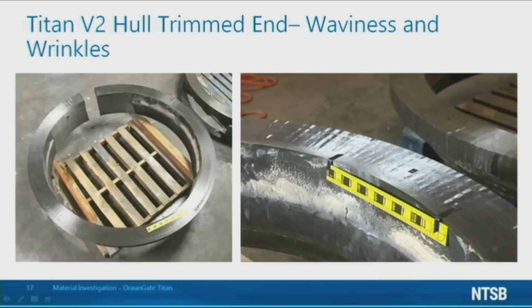The image on the left is an overview image of one of the trimmed ends. The image on the right shows a portion of the through thickness face under oblique lighting. The oblique lighting reflects off of the composite plies based on their orientation. The periodic light-dark reflections are an indication of the waviness of the layered structure.